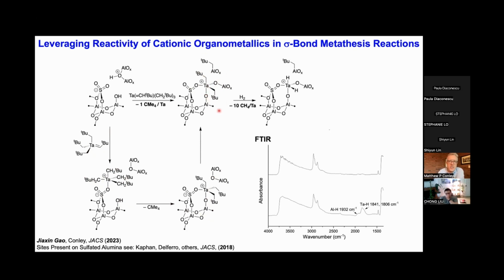You react this material with H2, we see 10 equivalents of methane come off per tantalum because the neopentane that we generate in that reaction is undergoing the hydrogenolysis reaction as we form the hydride. We can see this directly through FTIR. We can see the formation of Al-H bands, and we see the formation of Ta-H bands. When we contact with D2, those disappear, showing that they behave like metal hydrides.